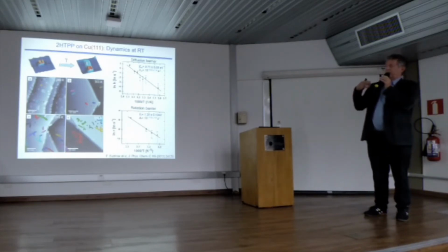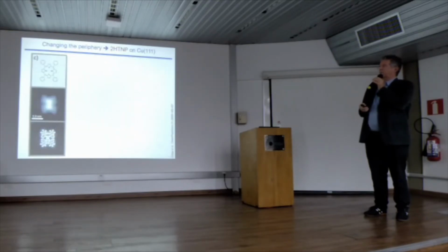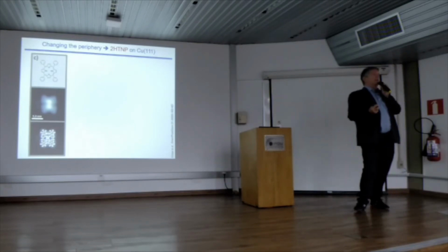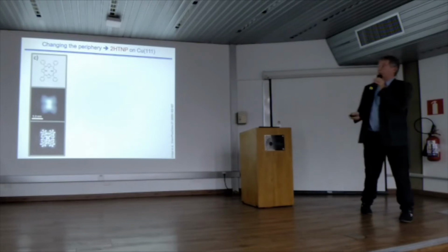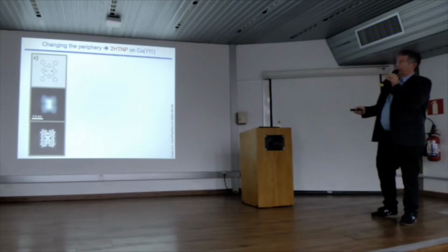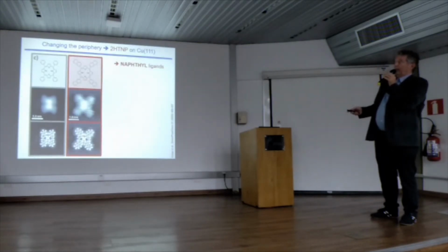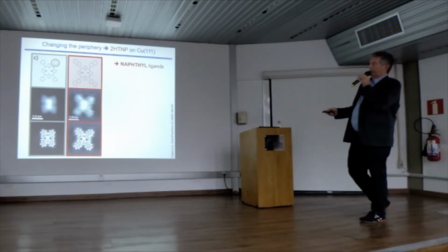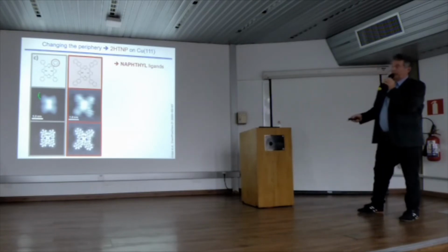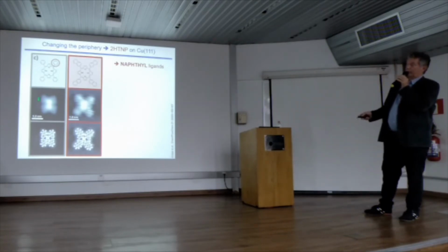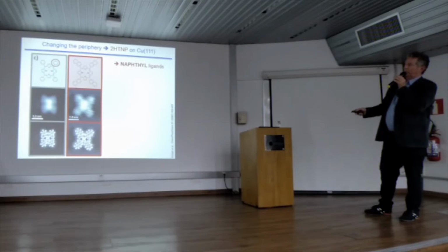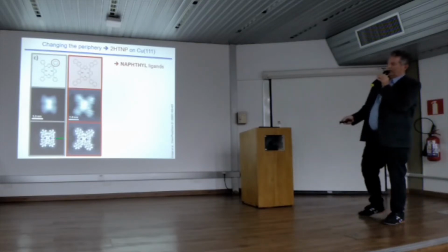But in the last years, we asked ourselves, is there a chance to change this property, mobility, to change the activation energy by modifying the molecule? And so what we did is we changed the periphery here. So we went to this molecule, from having phenyl groups to having naphthyl groups at the periphery. And then we imaged individual molecules. So this is the one shown here. And this is the one with the naphthyl groups. You see, it's more extended here because these groups are even more extended. And down here is an image superimposed.